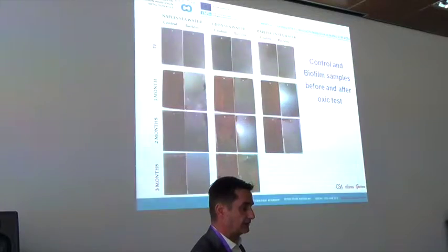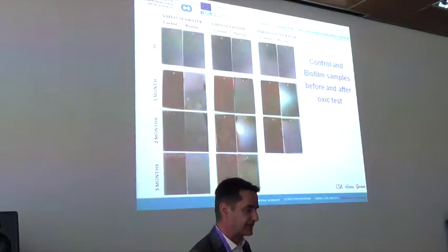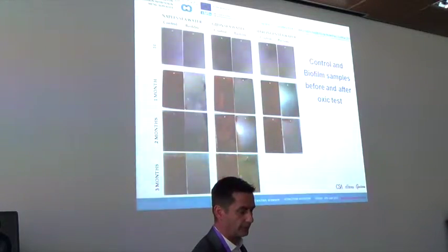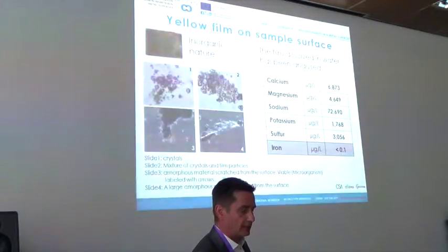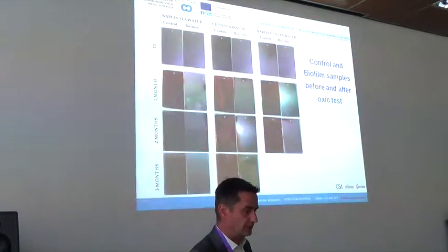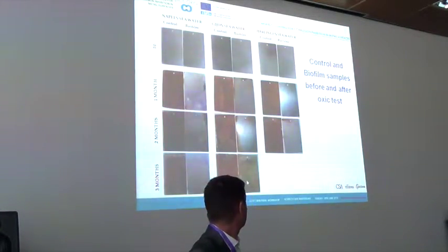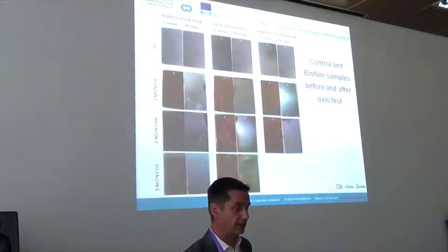The coating, the biofilm, works well and contrasts the rust. We have some defects on the edge of the samples, but they are due to defects in the painting of the coupon. And you can see also this coupon with this yellow-brown biofilm.